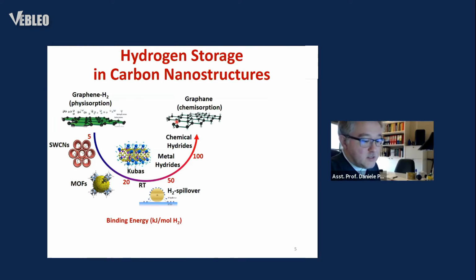In the second case, hydrogen can be strongly bound to the carbon network via chemisorption mechanism, as for example in hydrocarbons. In this case, the energy required to release hydrogen is too high, of the order of 100 kilojoules per mole, hence it's still impractical.